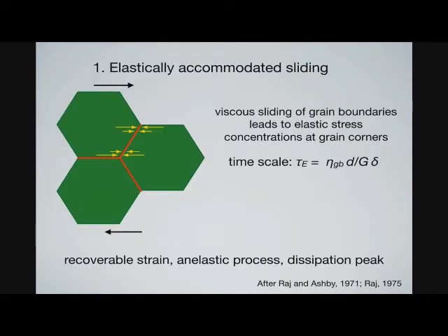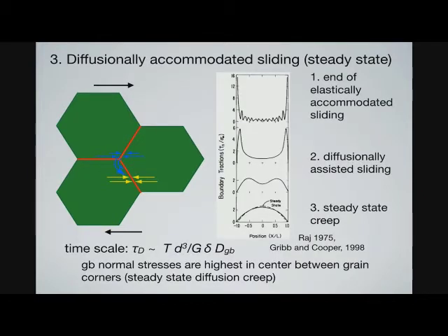And then we're trying to link it to models, and these models, going back to the 70s, of grain boundary sliding. So for seismic properties, grain boundaries are very important, in particular also diffusion, because as you apply a shear stress across this polycrystalline aggregate of your nice hexagonal grains, you have non-hydrostatic stress concentrations at grain corners, and that, as you saw earlier, stress concentrations then drive diffusion.